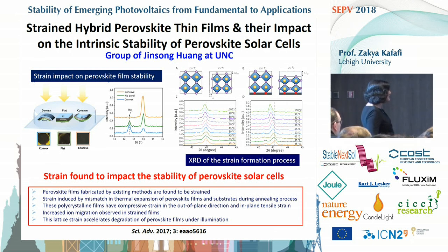So he showed that perovskite films fabricated by existing methods were strained. And this strain was induced by mismatch in thermal expansion of the perovskite films and substrate during the annealing process. So they have a compressive strain in the out-of-plane direction and in-plane tensile strain. This leads to an increase in ion migration, which was observed in this strained film, and the strain accelerated degradation of the perovskites under illumination. So very insightful studies in this regard.